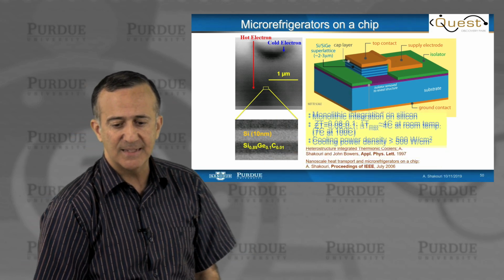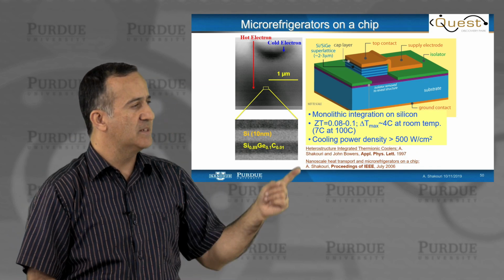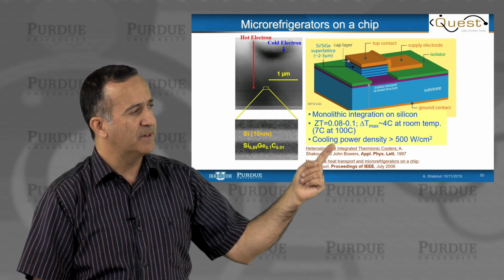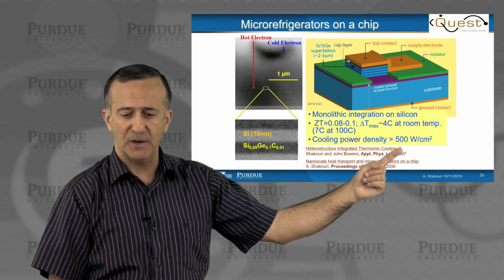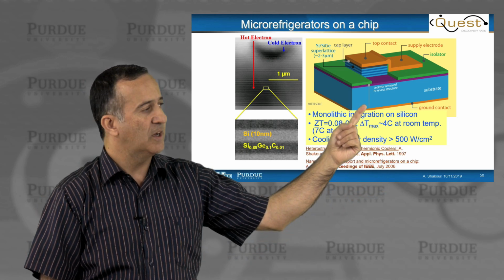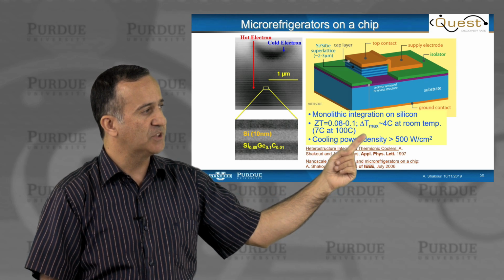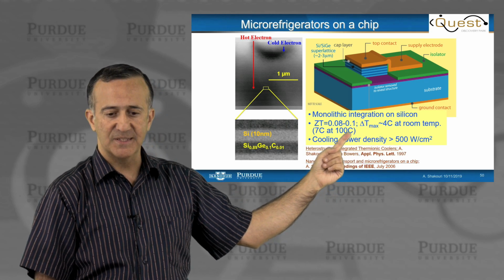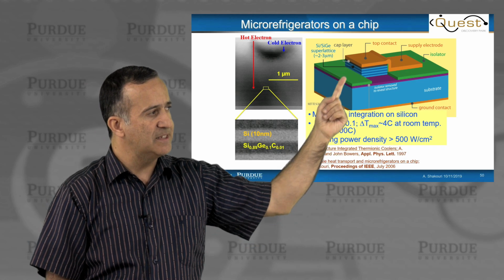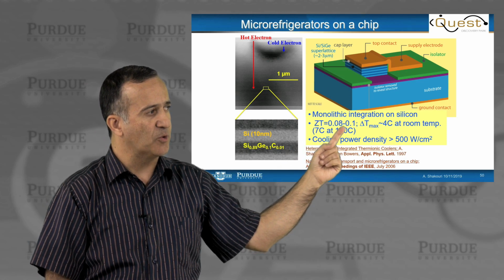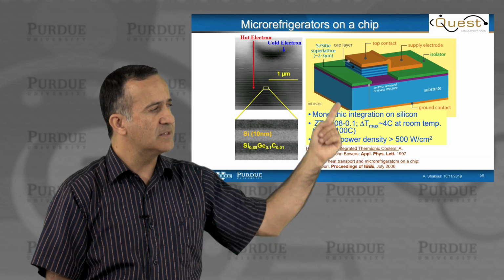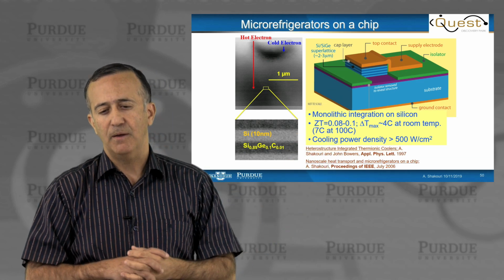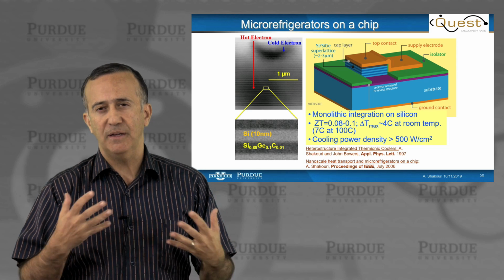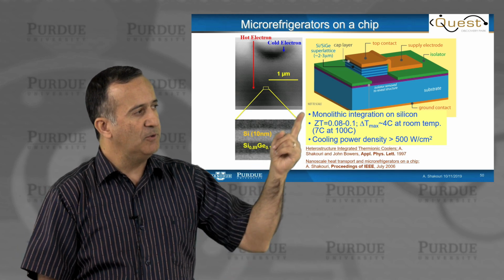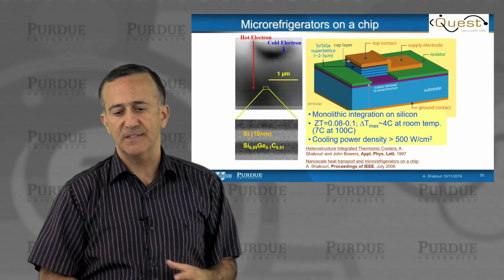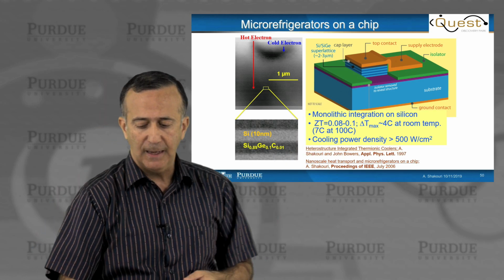And because there is less interface resistance, you can get cooling power densities of more than 500 watts per centimeter squared, with a cooling of about 4 degrees C at room temperature and 7 degrees C at 100 degrees Celsius, even though the material ZT is actually quite modest, 0.08 to 0.1. So this is a case where you don't need very high ZTs, but full integration and reduction of interfaces could play a role.